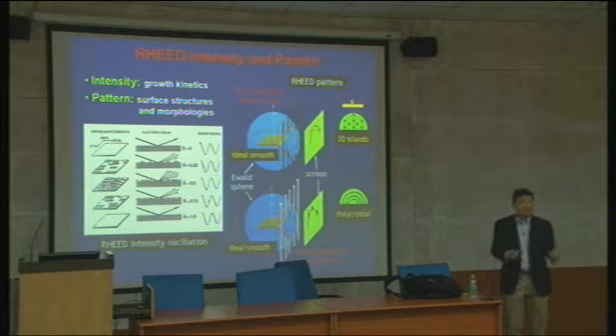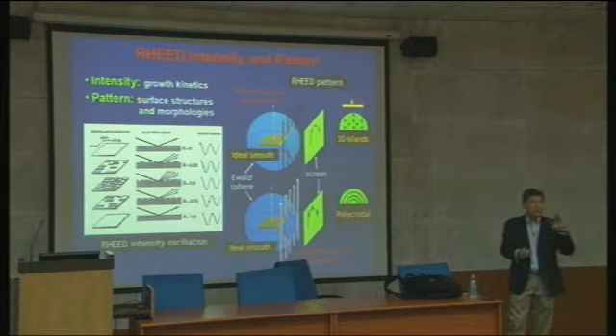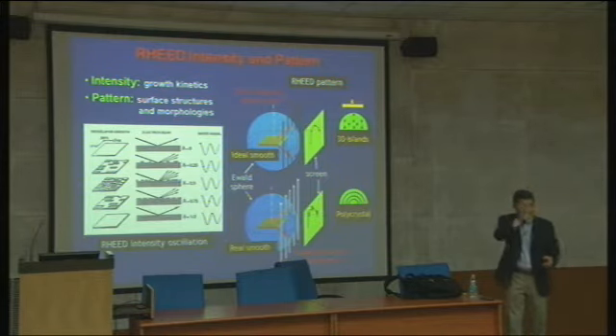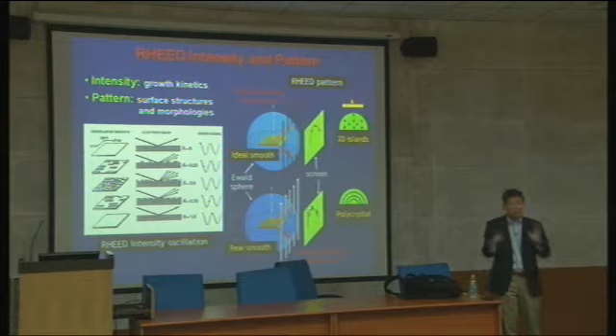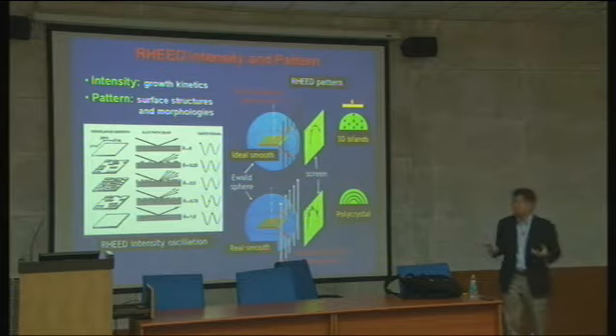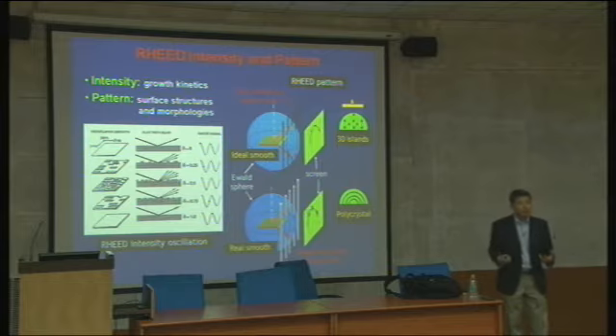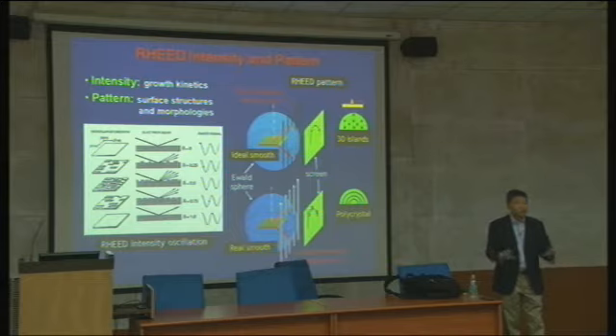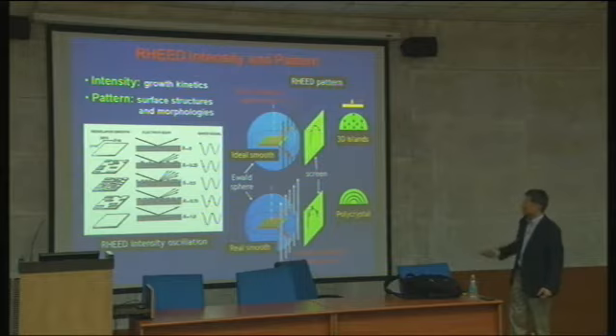So what that means is you really can see and control growth one atomic layer by one atomic layer, just by monitoring and counting this oscillation. So that's one way. This is commercially available now, but at the same time, you can actually see your electron diffraction pattern, very similar to TEM, as in lattice crystal structure imaging, and you can see either polycrystalline, amorphous, and 3D island.